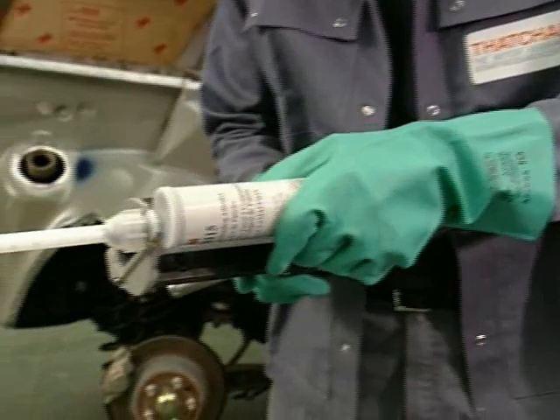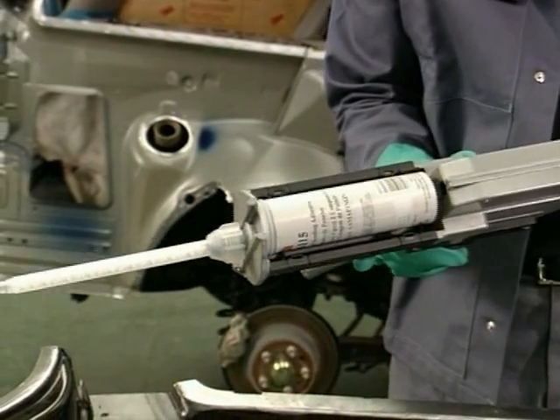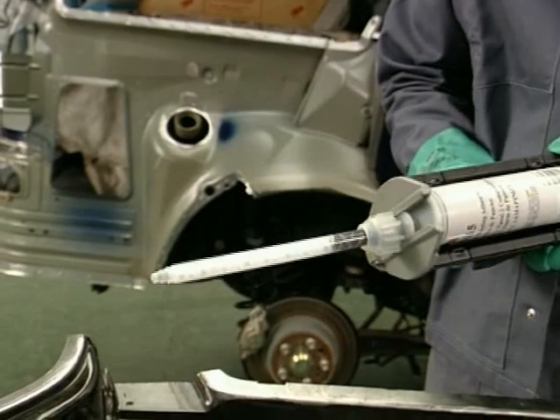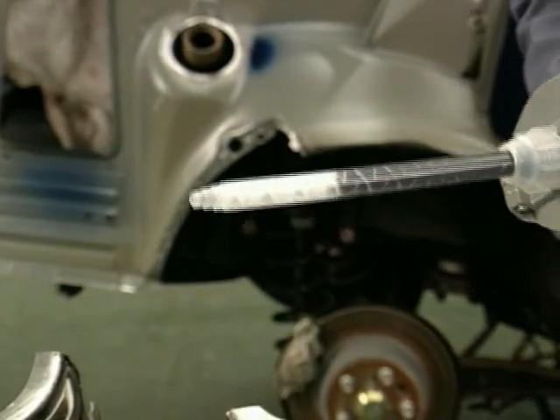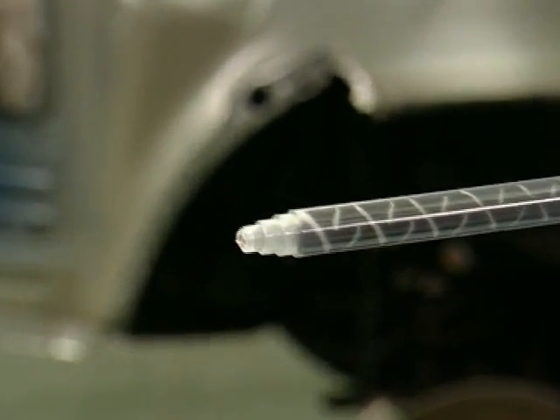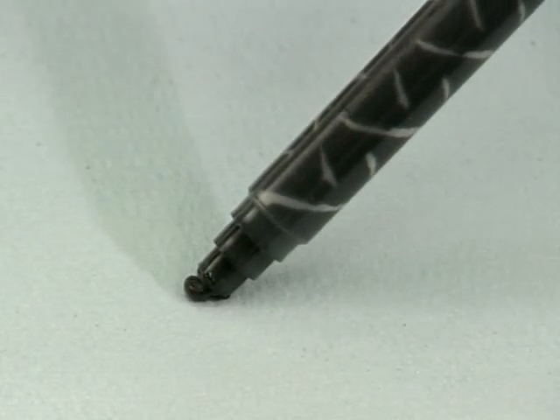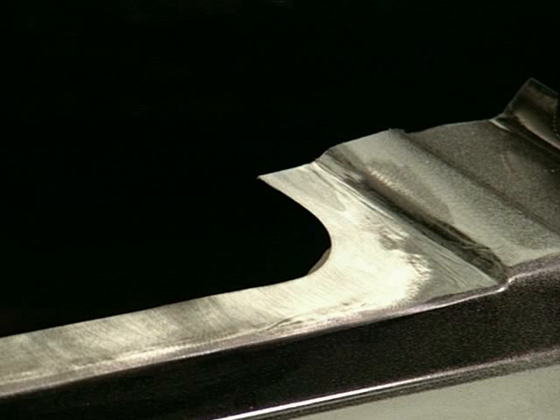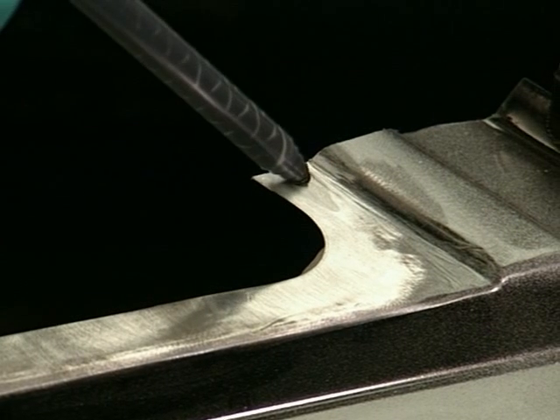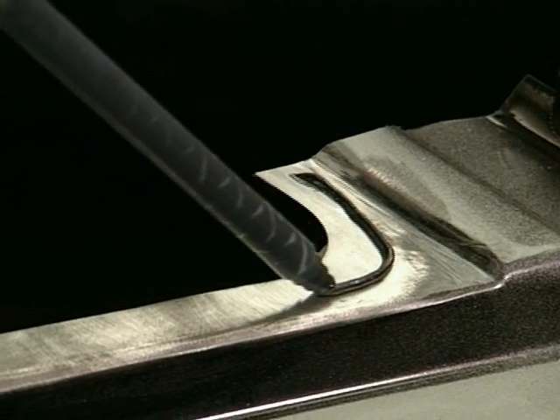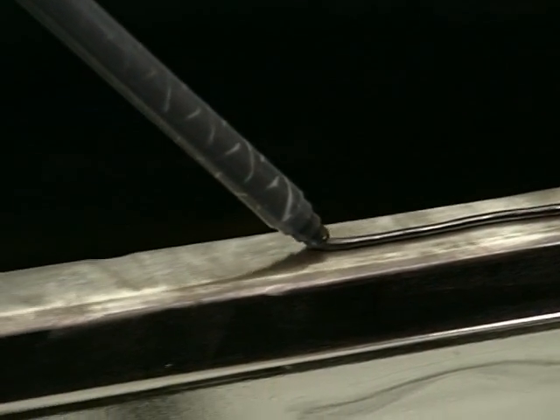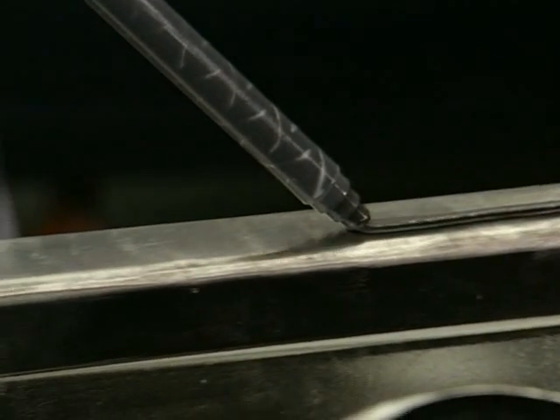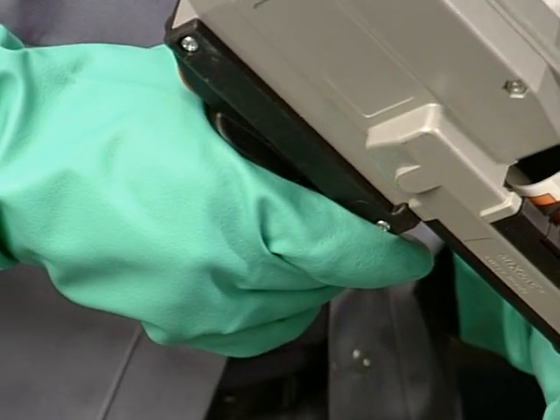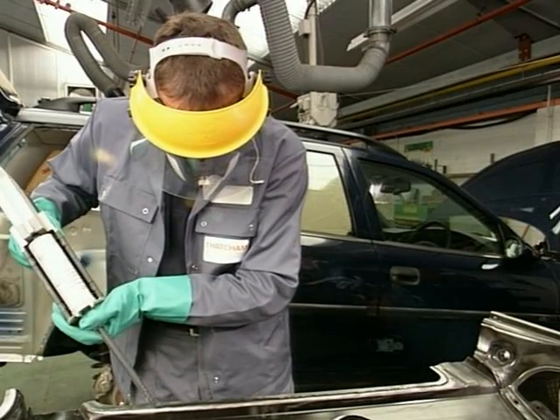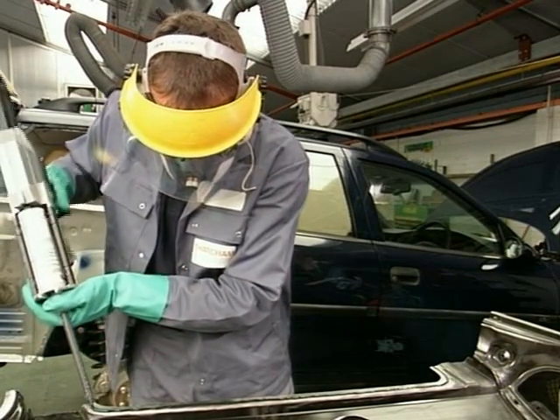3M8115 panel bonding adhesive is a two-part epoxy-based product with a working time of 90 minutes. The cure rate can be accelerated with a heat source, such as an infrared lamp. A check is made that the material is being mixed in the correct proportions as it's extruded from the nozzle. The adhesive can be used on all common substrates, steels, aluminium and automotive plastics. A bead is applied around the prepared panel edge. Because of its continuous contact with the bonded surfaces, it seals and bonds, reducing the risk of corrosion. Furthermore, it contains a built-in corrosion inhibitor pigment.